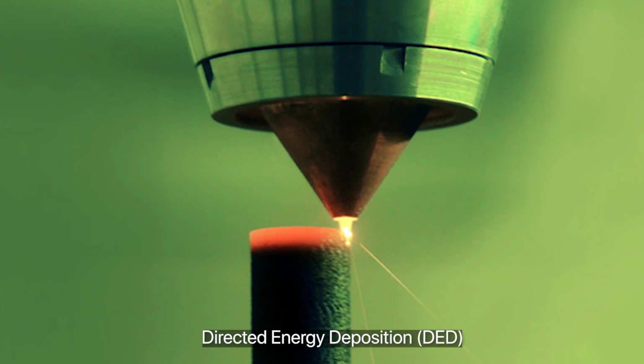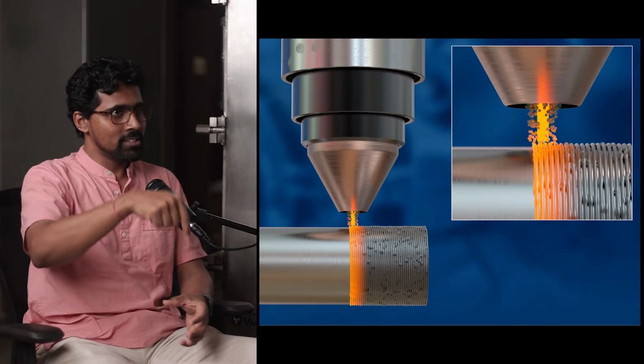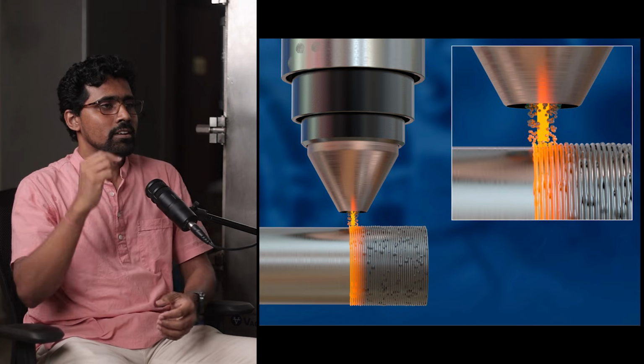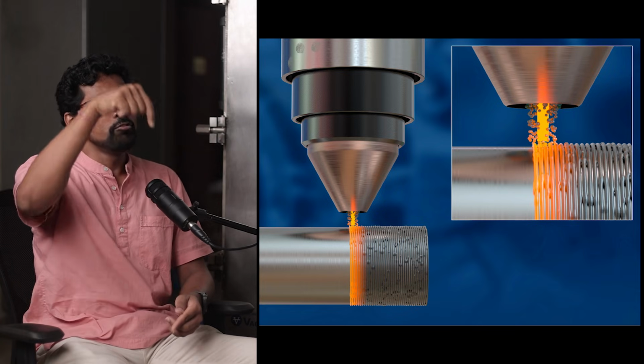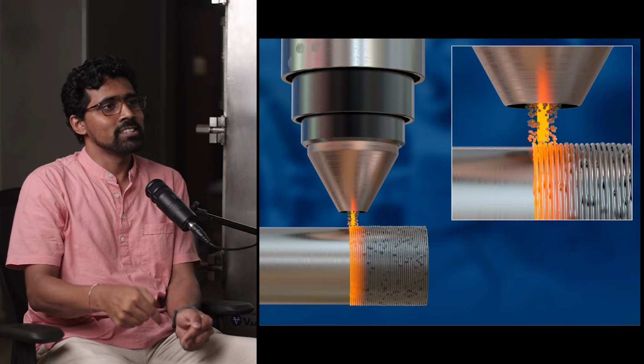So what happens is there is a nozzle. There are two coaxial nozzles. From the inner nozzle, the laser comes. From the outer nozzle, the powder comes. And the focus of the laser and the powder is the same. So you can control the power of the laser and the flow rate of the powder. Right. Okay. And now, because the powder is coming coaxially, you can keep your powder separately outside the machine, and you can work with very little powder, maybe as low as 100 grams, 50 grams of powder.